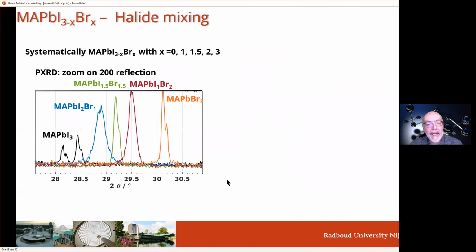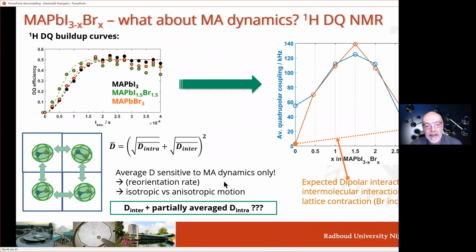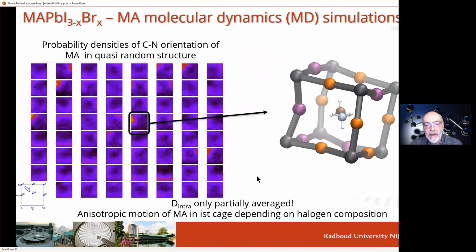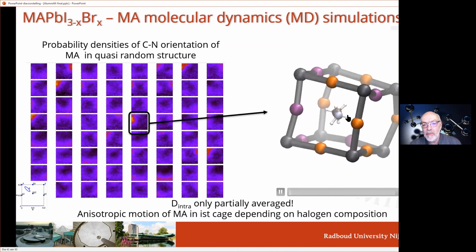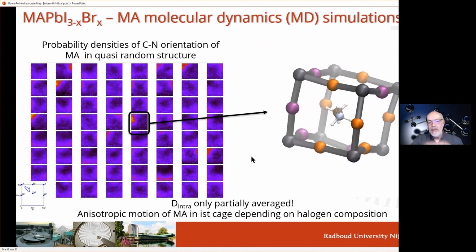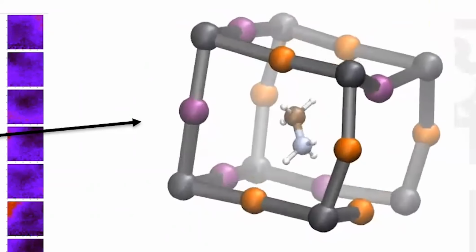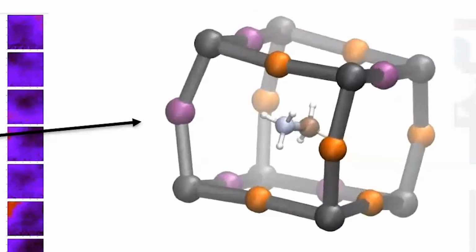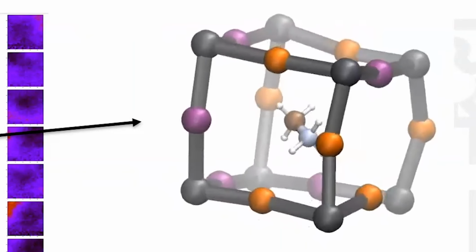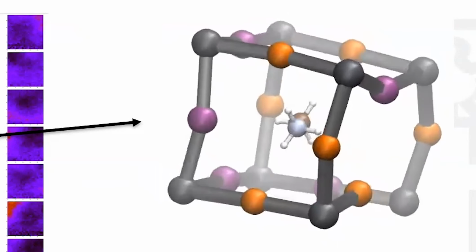Okay, and then we also looked at halide mixing. Again, we can do the lead NMR, and here we find, based on the dipolar interactions, that again the mobility of the cation is influenced by the composition of the lattice. We find nice, say, random mixing of bromine and iodine in this case. But when we now look at the dynamics of the methylammonium, it doesn't rotate completely randomly anymore. And we can tell so from our NMR spectra, and our theory colleagues can now also simulate that in these so-called molecular dynamics